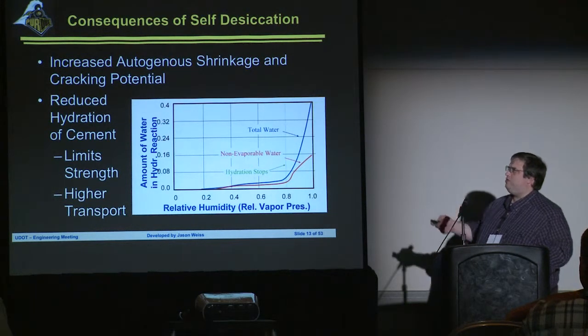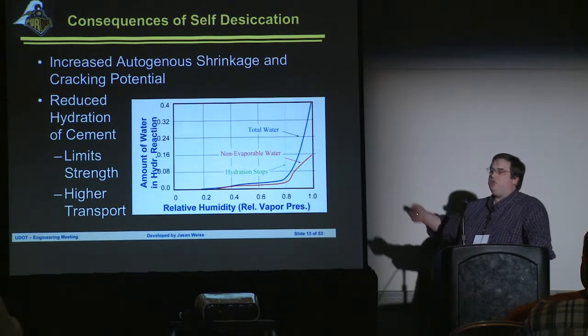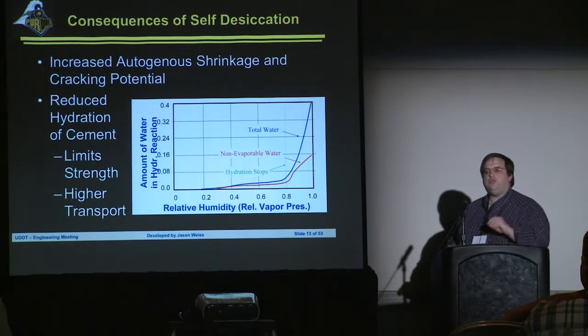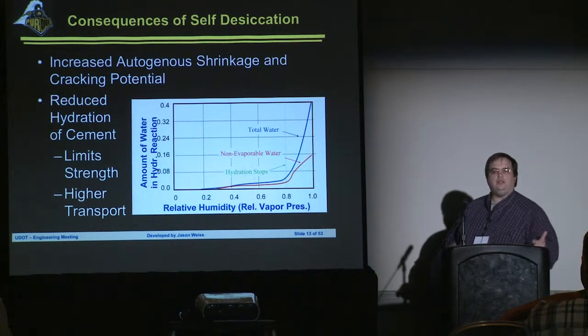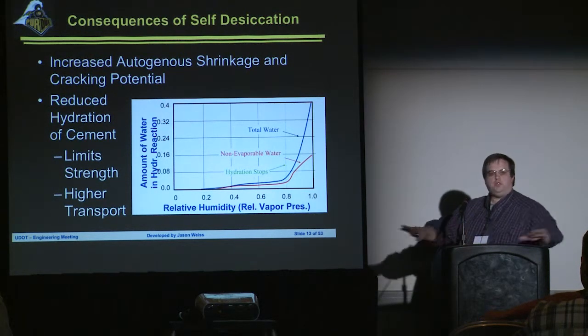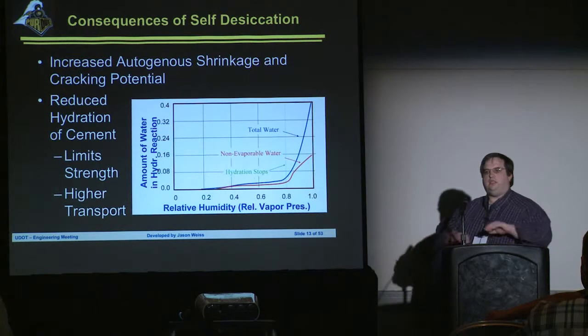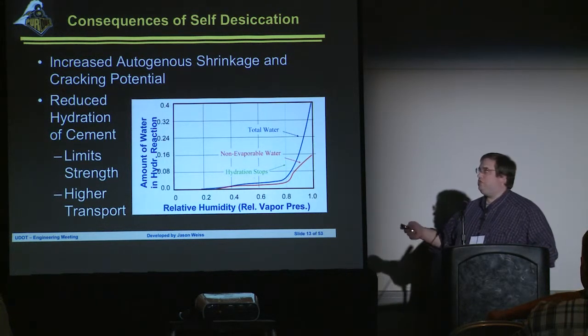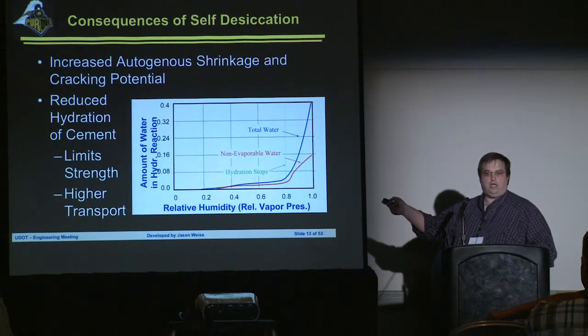So the consequences of self-desiccation? Well, we're going to have increased autogenous shrinkage. This is shrinkage that occurs without moisture loss, shrinkage that occurs without a temperature change. So even if you take your concrete, you put visqueen on the top, you put your curing compounds on the top, you put your sealers on the top, it's still shrinking because of this chemical reaction.